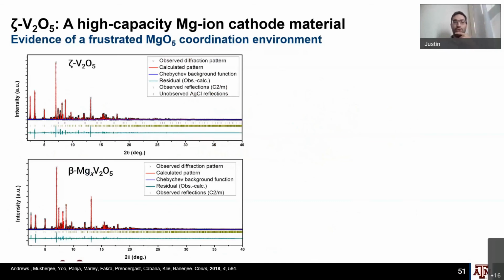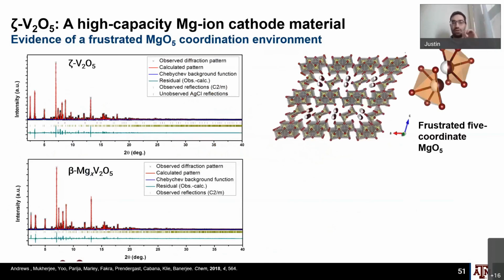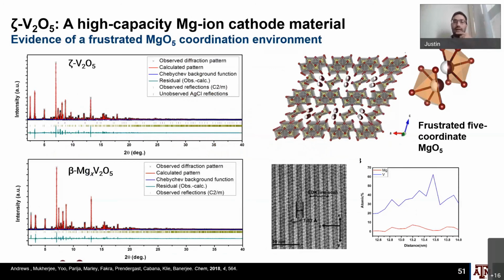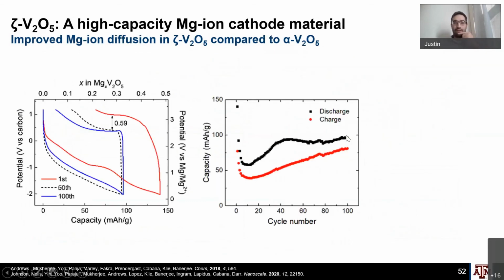So we were able to show through X-ray diffraction, solve these structures, and basically show that we do actually get magnesium in here, and it sits exactly where we expect, and we can actually image this magnesium through EDX within these tunnels. This was very exciting work, and we were able to show that we can reversibly intercalate magnesium here very well at the time.